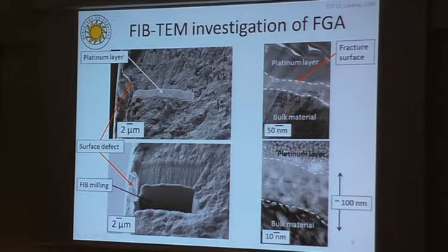If we take a detailed look at this fine grained layer, we can see that it is composed of many fine grains of nanometric size. It was further indicated by the presence of diffraction fringes, which had different orientations in each of these small grains.